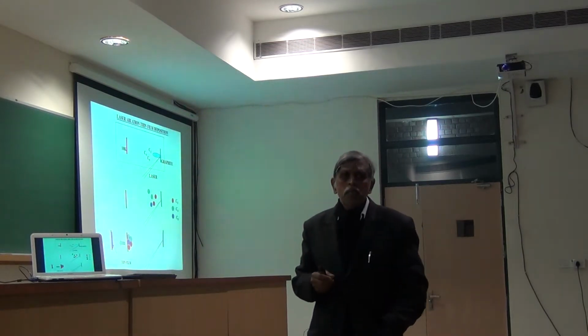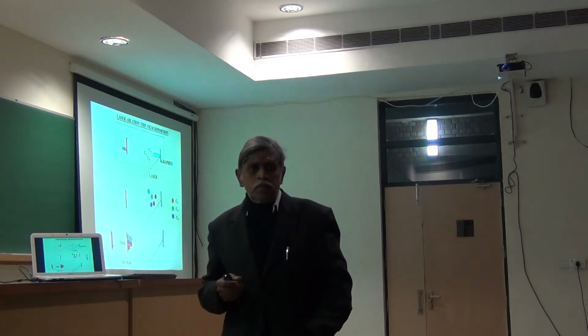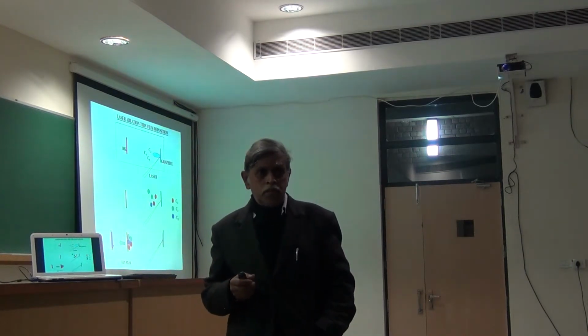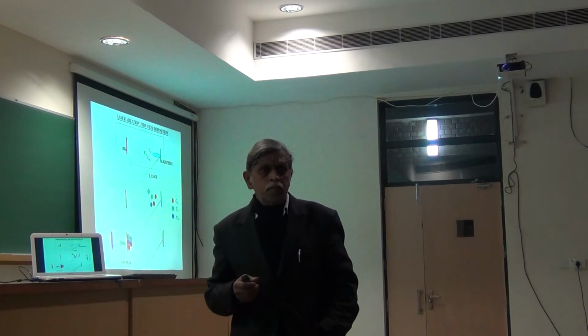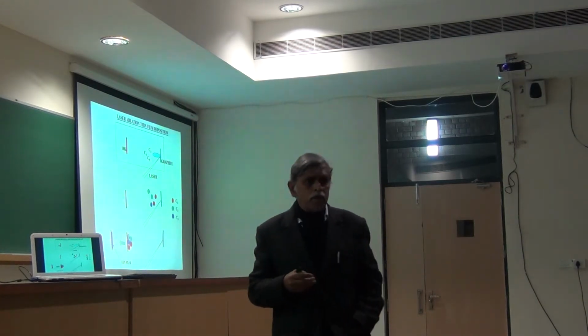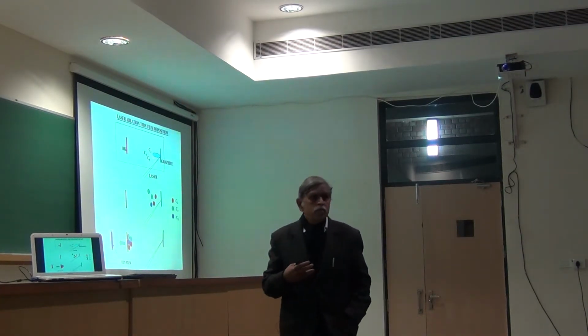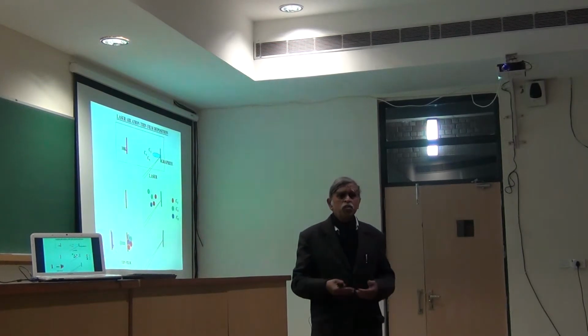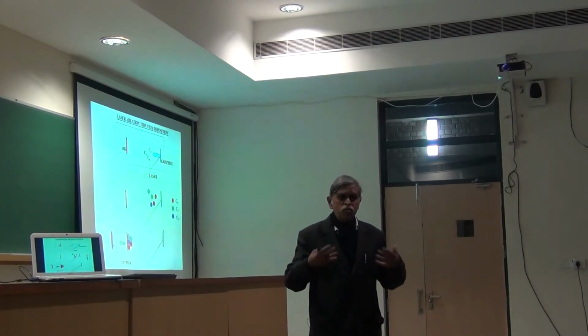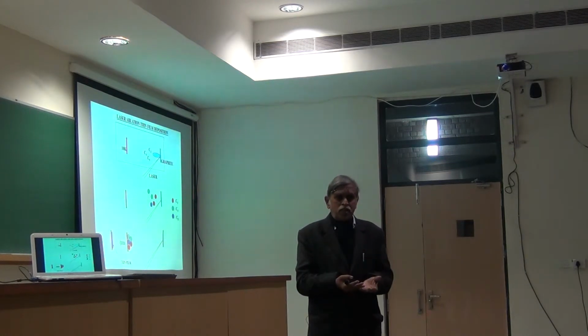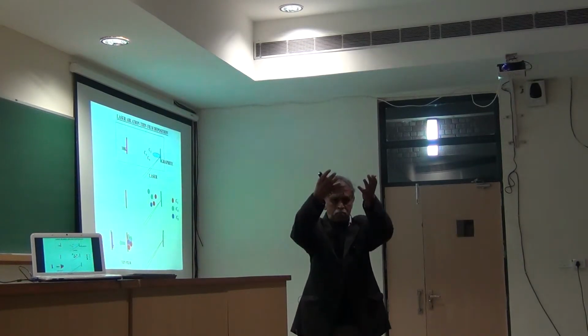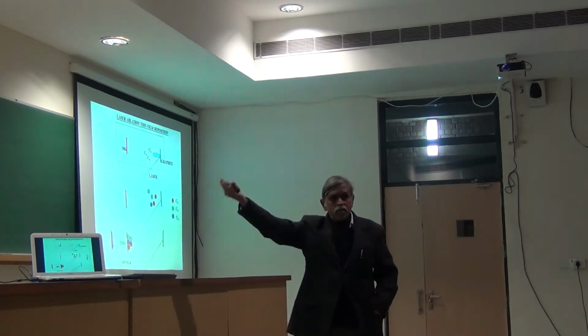Once these species deposit on the 10 Kelvin cold finger, they can't react with one another, but can't they dissociate? Can each C5 cluster dissociate? If they dissociate, they have to dissociate unimolecularly. So let's say if I have a C3 cluster, and it's in a ground state, and let's say the ground state is bound, then of course they're not going to dissociate, because if I have to dissociate them, I have to take them up to a barrier which will then dissociate them.